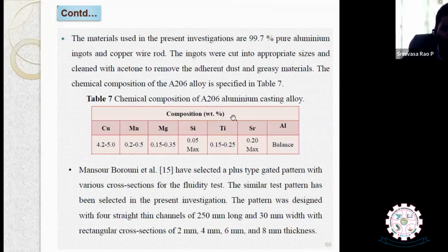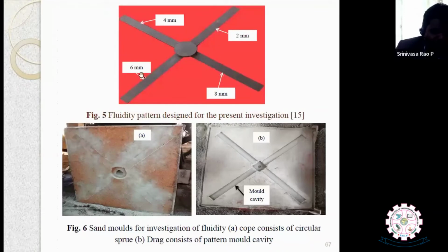What is actually the composition of the A206 alloy? You can see the copper percentage is 4.2 to 5, and of course there are other miscellaneous elements, but mainly aluminum and copper. Aluminum is the major one, copper is the second, and the remaining are very minor. So we have used pure aluminum, 99.7, and made the A206 alloy. This is actually used for testing the fluidity.